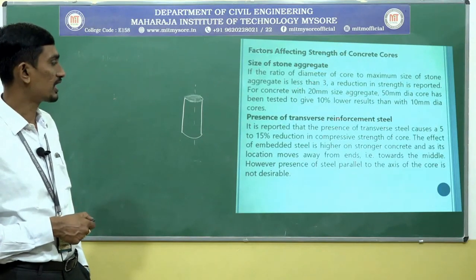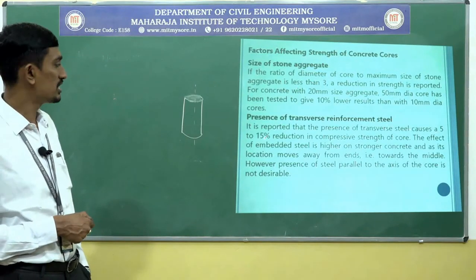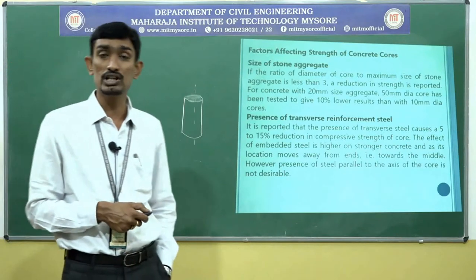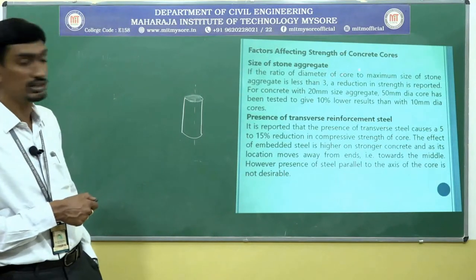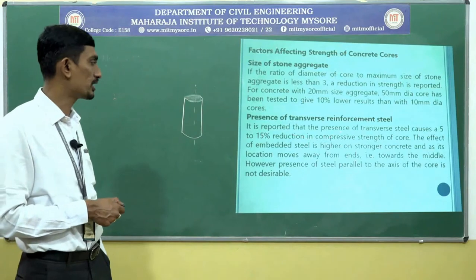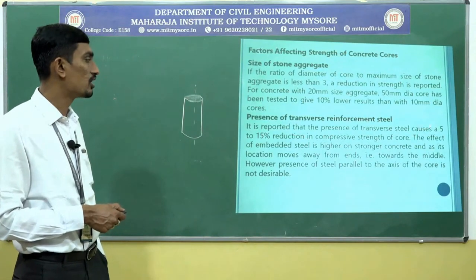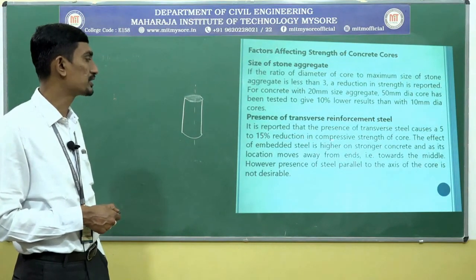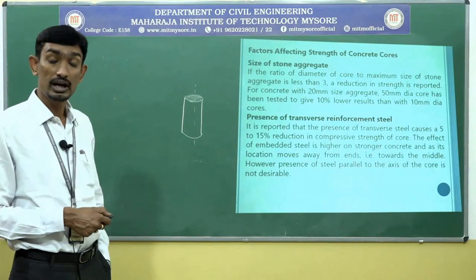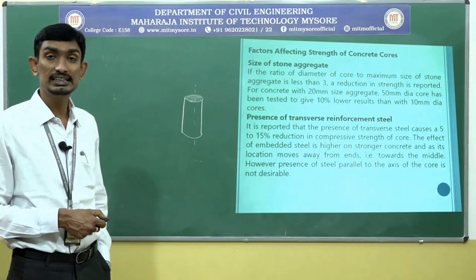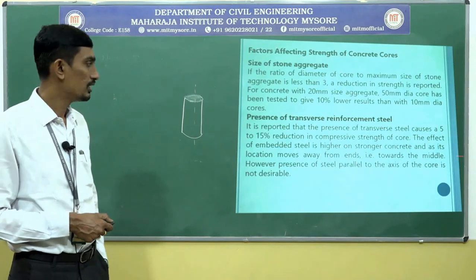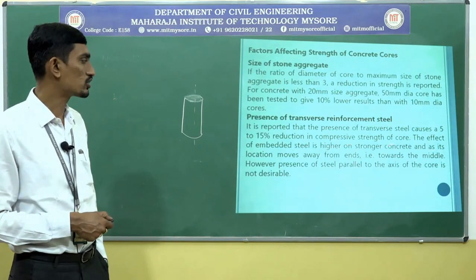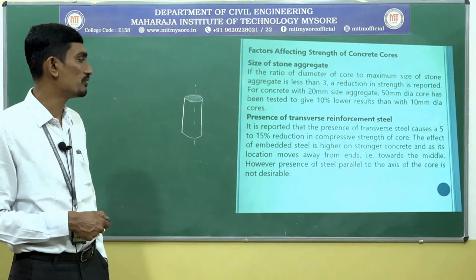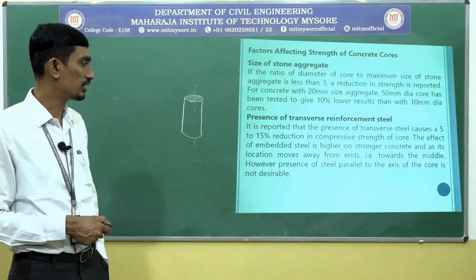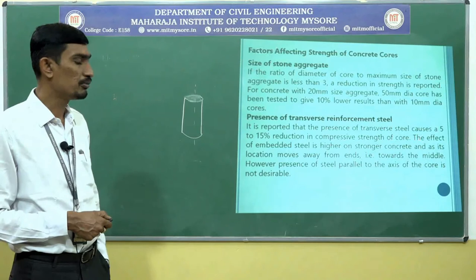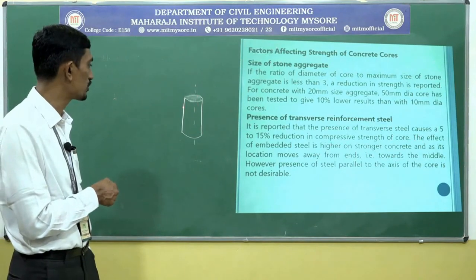Next, presence of transverse reinforcement steel. If there is any steel inside the concrete core, what is going to happen? How will it affect the strength of the concrete? See here. It is reported that the presence of transverse steel causes a 5 to 15% reduction in compressive strength. Hence, avoid reinforcement inside the concrete core. Is it clear? The effect of embedded steel is higher on stronger concrete, and as its location moves away from the ends, that is towards the middle, the effect is more in the middle portion compared to the end.